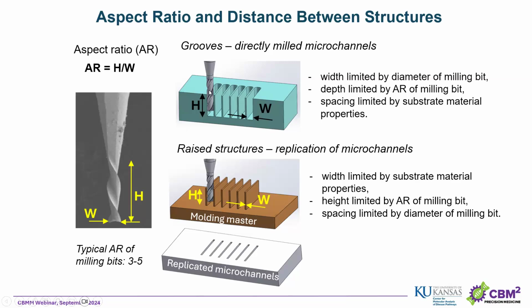So, for example, if you're thinking about the direct milling, as I mentioned, the smallest width of the channel will be limited by the diameter of the milling bit, but at the same time, the depth will be limited by the aspect ratio, right? So if we take a 100 micrometer milling bit, the narrowest channel we'll be able to make is 100 micrometers, give or take, but the depth will be 300 micrometers, right? But at the same time, we can position the channels, the spacing between channels, it's really dependent on the type of material we're using, right? Whether this really tiny wall is not going to collapse and we can make a final device out of it.